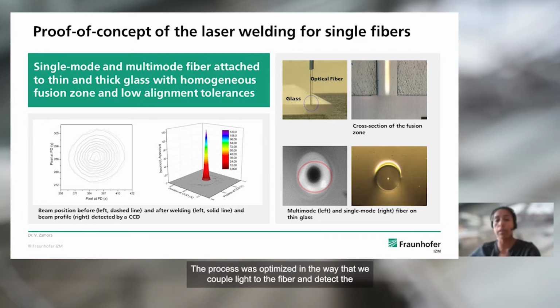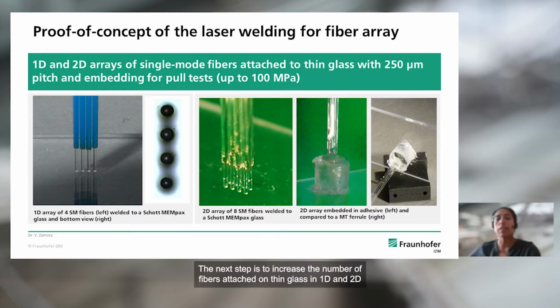The process was optimized in the way that we coupled light to the fiber and detected the corresponding beam profile using a CCD camera. The camera was placed under the glass piece. Here we found a good self-standing of the fibers, acceptable homogeneity of the fusion zone, and position tolerance of around 2 microns after welding.